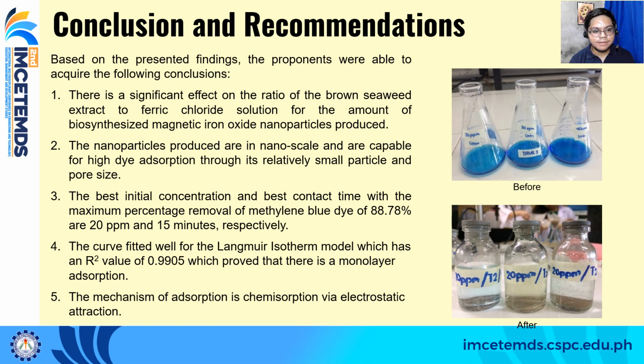Number four, the curve fitted well for the Langmuir isotherm model, which has an R squared value of 0.9905, which proved that there is monolayer adsorption. And lastly, the mechanism of adsorption is chemisorption via electrostatic attraction, which is according to the kinetics data that well fitted to the pseudo second order model.